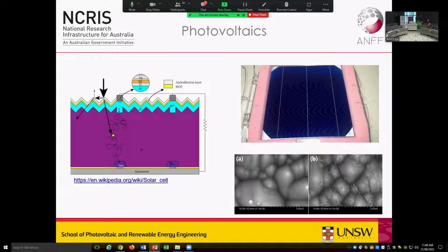This is an example of a maskless etch where you're just dipping the silicon in, and the natural nucleation points and pyramidal structure of the silicon lattice will give you these rough pyramid structures. Why I had this slide in terms of laser processing, this is one area where laser processing is really important to future developments, okay? A lot of photovoltaics, and the ramp up of photovoltaics is just incredible, the amount of this stuff being rolled out. But lasers are often used to mark out the bus bars for collection on the wafers and things like that. That's one example there. We do have several researchers from the big photovoltaic group at UNSW coming and using our facilities to do various things on their wafers.